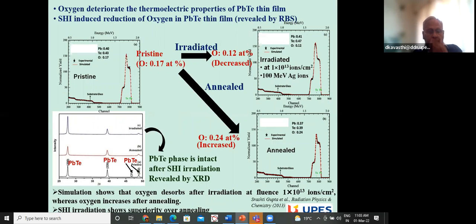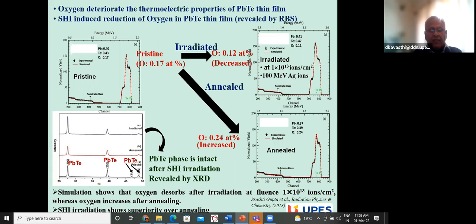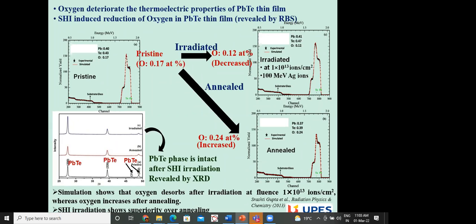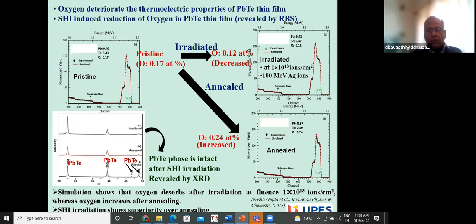Lead telluride formation is also proven by Rutherford backscattering, showing how mixing is taking place. Additional information: in the pristine sample, oxygen content was 0.17 atomic percent, but after irradiation it goes down to 0.12 percent. Whereas if you anneal it, oxygen increases — which is not desirable. These are key results from PhD student work.